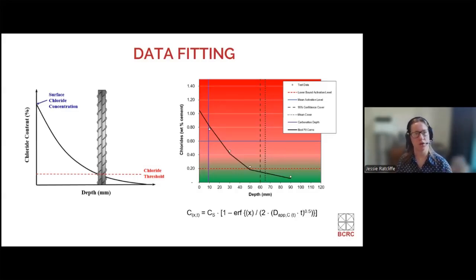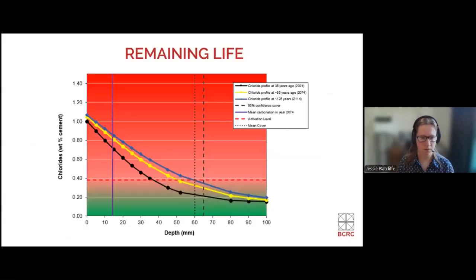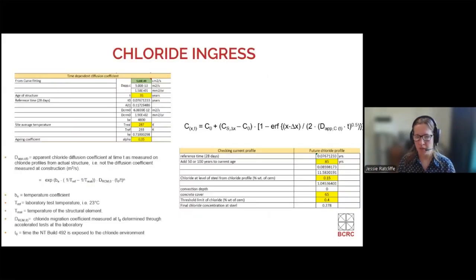So that is based on site data. That's not the diffusion coefficient that would have been measured at construction or present in your spec or your mix design. That's based on what we've really found. And using the equations, we can then take our diffusion coefficient and calculate curves for the chloride amount at different times using the current age of the structure, the average temperature, either from BOM or from site measurements, and then the aging coefficient.